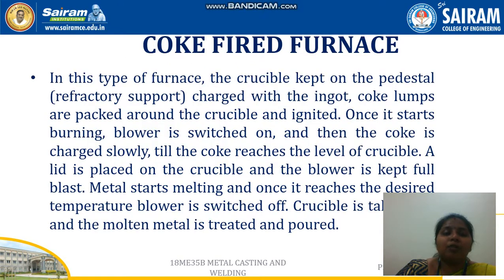So in this coke fired furnace, the crucible is kept on the pedestal, that is a refractory support, charged with ingot, and coke lumps are packed around the crucible and ignited. Ignited means it's getting heated up. So once it starts burning, the blower is switched on, and then coke is charged slowly till the coke reaches the level of the crucible. A lid is placed on the crucible and the blower is kept at full blast. Metal starts melting once it reaches the desired temperature. Blower is switched off.